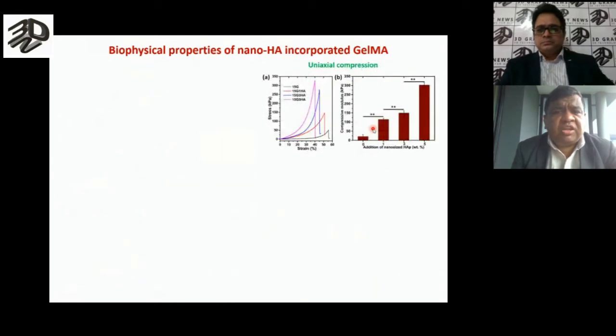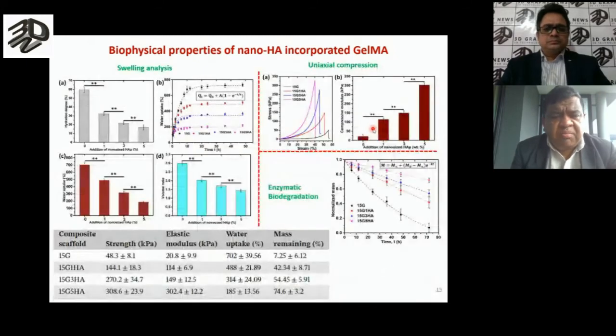We are getting strength up to 300 kilopascal, which is quite a clinically acceptable number. And this table gives you a summary of that. What are the strength properties we are getting? G stands for gelatin methacryloyl, HA stands for hydroxyapatite. With 5% hydroxyapatite, we could boost the strength to more than 300. Elastic modulus is also more than 300 kilopascal and so on.